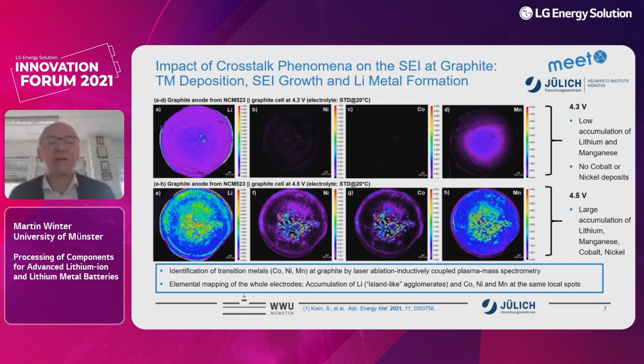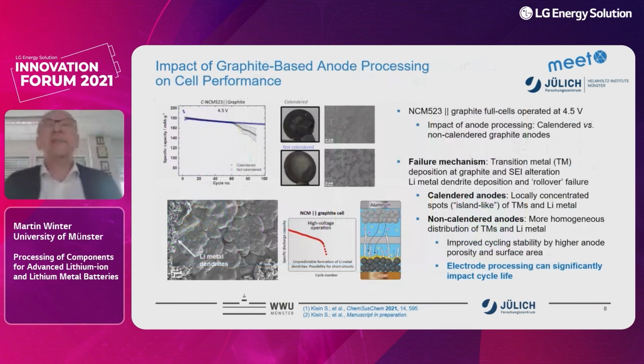What we have found out is that nickel, cobalt, and manganese deposition takes place because of transition metal dissolution, migration and diffusion to the anode, and then deposition at the anode. And these are then the hotspots for lithium metal deposition because the SEI has altered, and then lithium ions cannot integrate into the graphite material as before. And this is very much influenced by electrode processing.